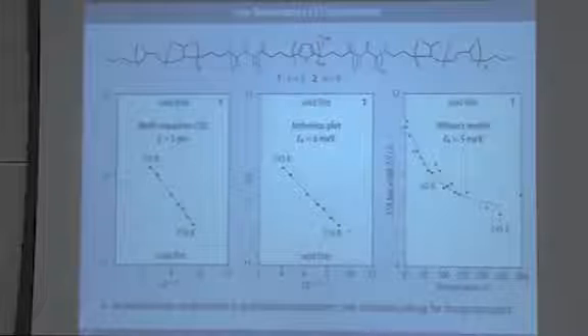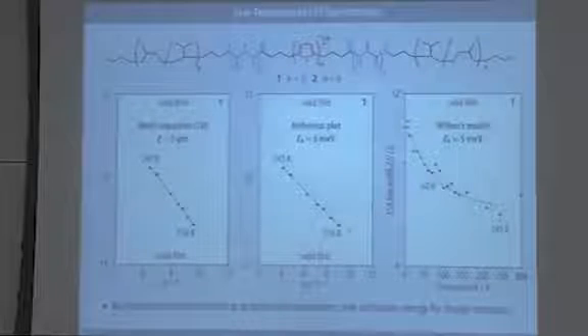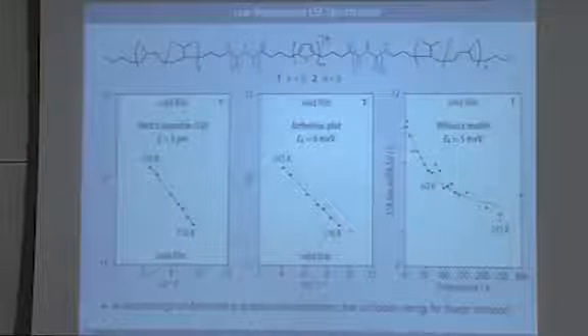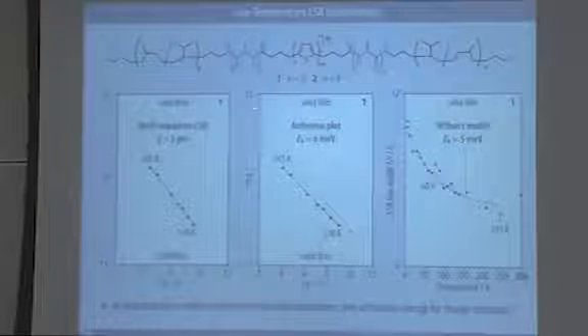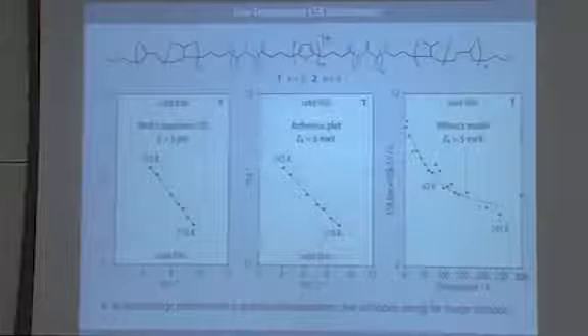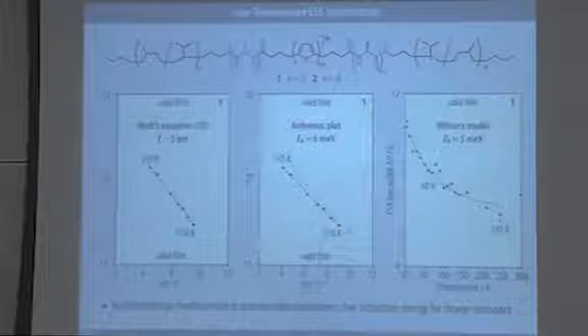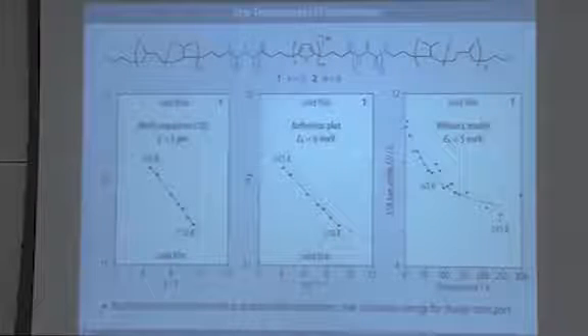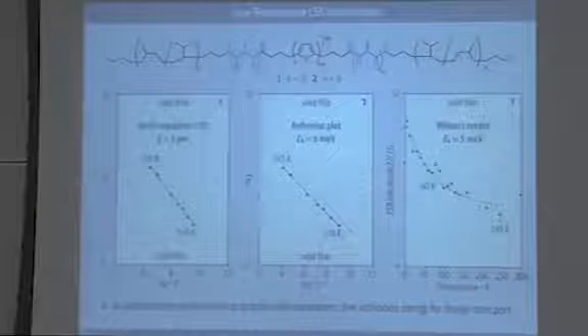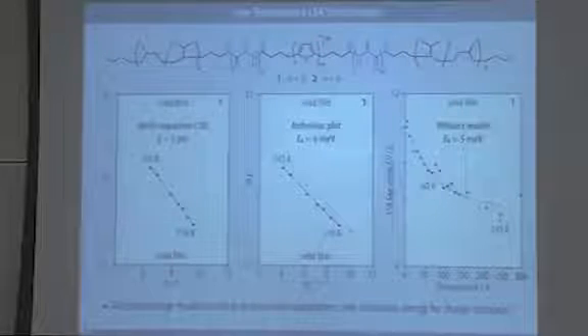This can also be seen from the fact that if you do an Arrhenius plot of our data, again we obtain a good relation, albeit over a relatively small range of physical values. But we obtain an activation energy which is 6 millielectron volt, which in this case I would say is not physically impossible, but it's actually very small compared to typical polythiophene materials, which is more on the order of 50 millielectron volt or higher, probably even rather like 200 millielectron volt.